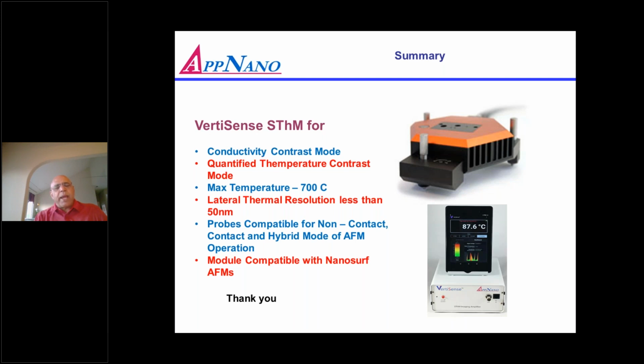The probe and the unit is compatible, and they can do it. It can do the quantified temperature contrast mode. You can measure the actual temperature if you calibrate it. The maximum temperature which we have seen can go up to 700 degrees Celsius, and the lateral thermal resolution, we have seen 20 nanometers, but regularly we can see 50 nanometers. Then you can use these probes in a contact mode, non-contact mode, or hybrid mode of operation depending upon your applications. Sometimes in the hybrid mode people want to have intermittent contact with the sample in some ways, so you can do those also.